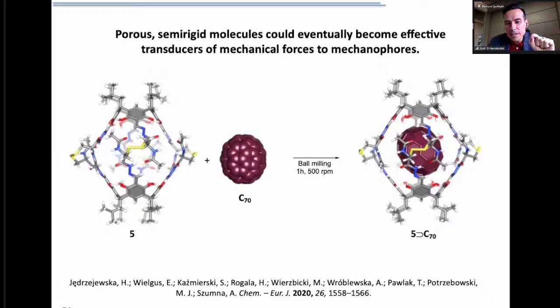And 2 years ago, a group of colleagues demonstrated that perhaps porous semi-rigid molecules could also be used to transduce mechanical force to mechanophores. And they demonstrated it this way. So they had molecules such as 5, which are porous. And when they ground together capsules like 5 with fullerene such as C60 or C70, they observed that at the end of the milling process, there was an encapsulation that had occurred.